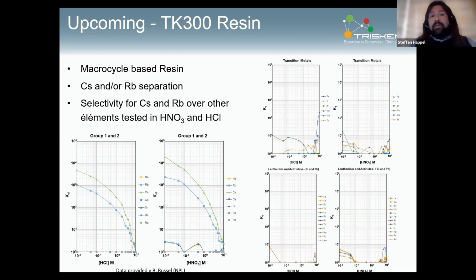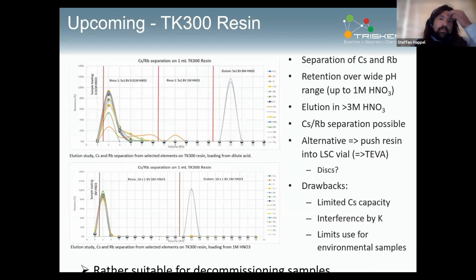The selectivity for the cesium and for the rubidium over other elements is quite high. Extraction is very elevated from dilute HCl and dilute nitric acid. You can extract both of them up to about 1 molar nitric acid. After that, you start to elute both the cesium and the rubidium. So basically, you could imagine two different types of applications. One is water samples, acidified water samples, given the quite high distribution weights of the cesium and the rubidium.